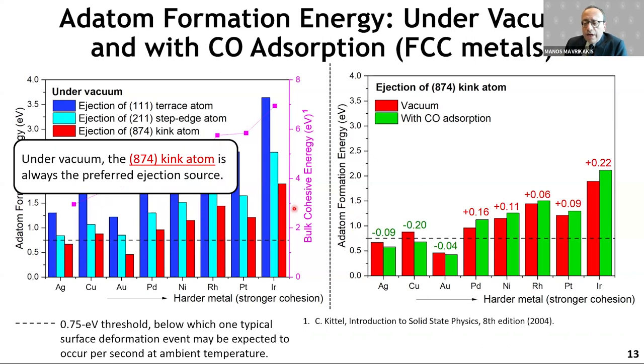Now, if you look on the right-hand side of this plot, we've taken the red bars from the left. That shows you how difficult it is to eject metal atoms from the kink site. And then we compare with the green bars, new data, that tells you how difficult it is to eject an atom in the presence of CO. That is the dilute limit of CO: one molecule in the unit cell, it's 1/14th of the monolayer.